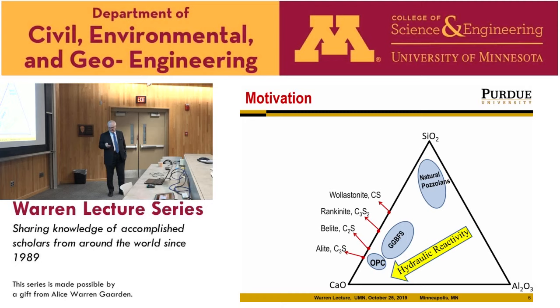To give you an idea of what is involved, this is a phase diagram that has the three basic oxides present in cement: calcium oxide, silicon dioxide, and aluminum oxide. As we go toward the corner here, which has a lot of calcium oxide, we increase the hydraulic reactivity. So ordinary Portland cement is located here, has a lot of calcium, has silica, and a little bit of alumina. And the C3S and C2S are the main components of Portland cement. But there are other compounds here, like rankinite or wollastonite, that are also in the region, but because they are far away from the CaO location here, they are not hydraulic. Right?